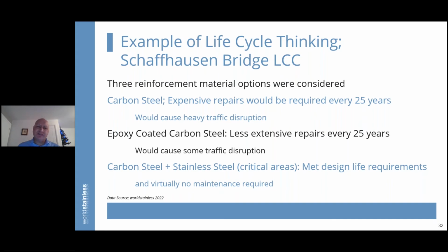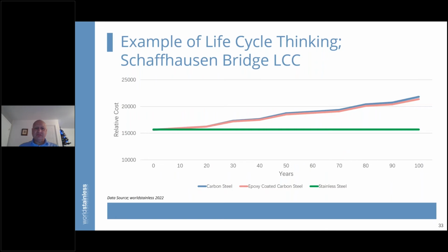But hey, what would this cost? And here's the life cycle cost chart. So what's interesting is that stainless steel requires pretty much no intervention. It doesn't degrade, it doesn't corrode in this sort of environment, even with the heavy use of de-icing salt. So the cost at the start is the cost at the end in this example. The other products have increasing costs, but when you look at the start point, the difference between the two, because this was careful selection of stainless steel for the critical areas where corrosion products would exist very quickly, there was very little difference between the initial cost. It was about 1%. So not much at all, and not a reason not to choose stainless.